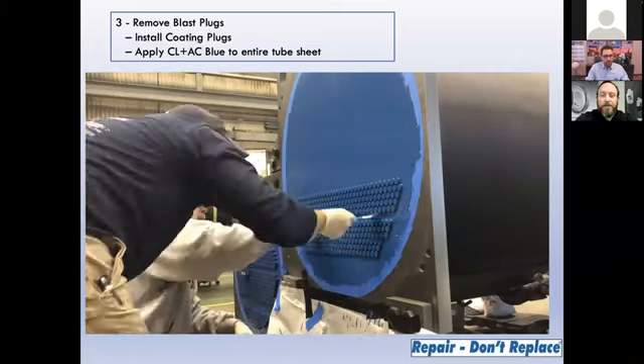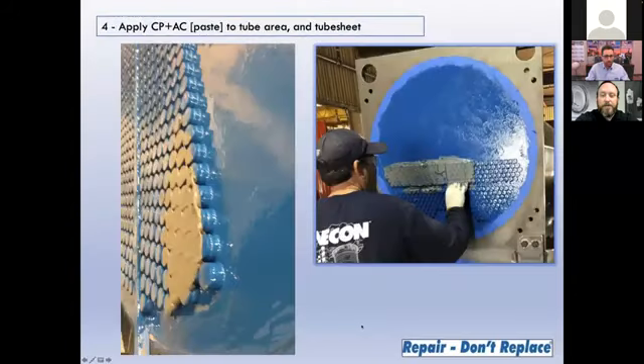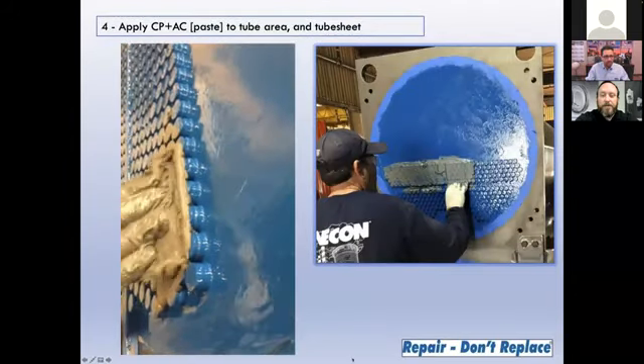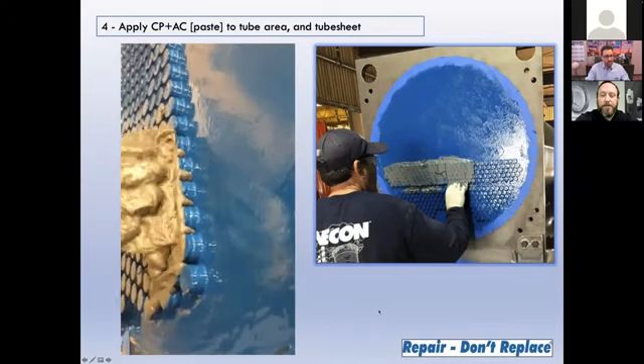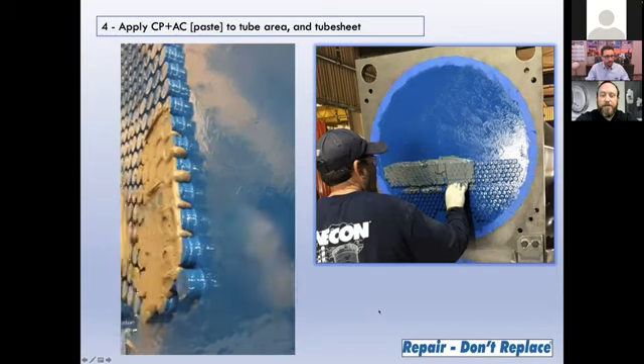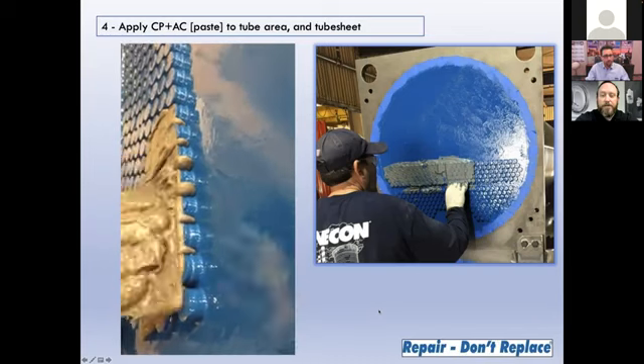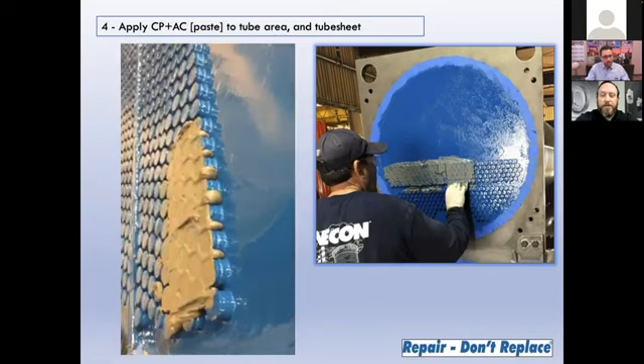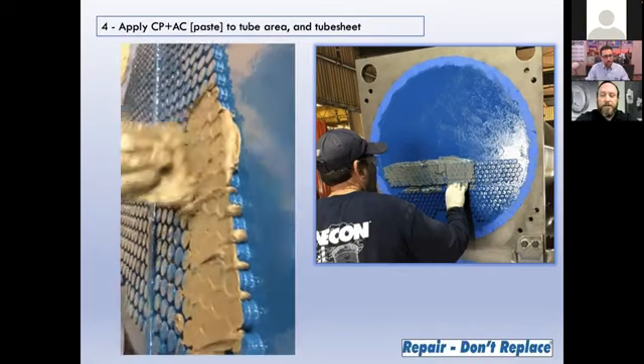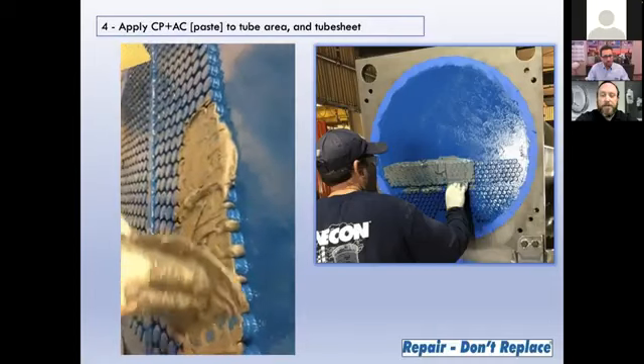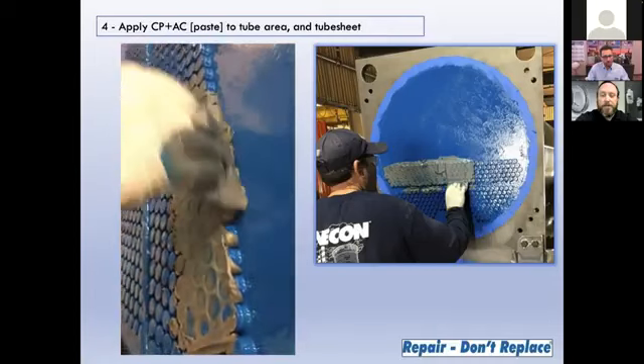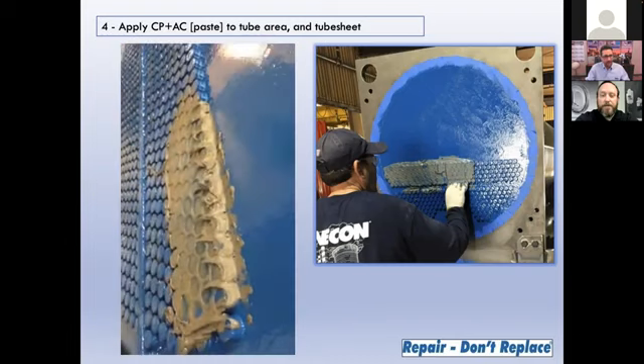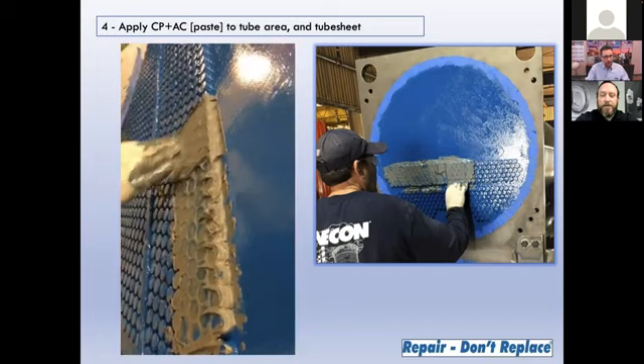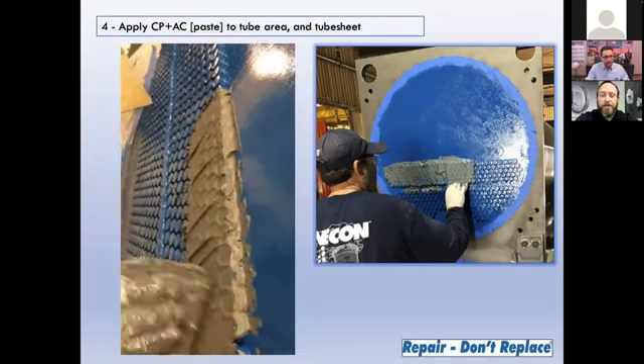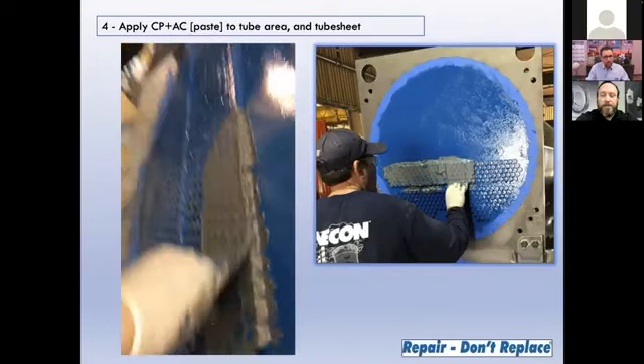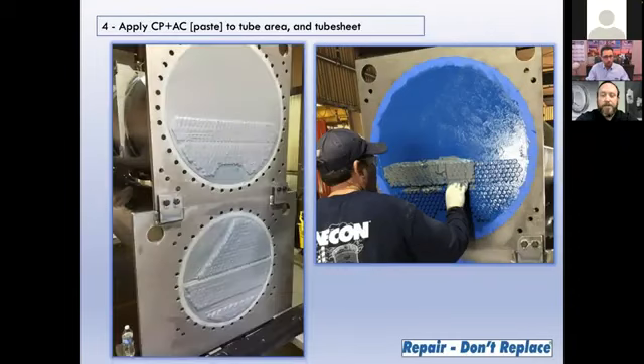The next part of the process is to apply the CP plus AC to the tube sheet surfaces. In this video, you'll see that the CP plus AC is pressed firmly in a vertical fashion, pressing down in between the tubes, getting intimate contact between the tube sheet, the tubes, and the CP plus AC, pressing firmly, going vertically, then horizontally, making sure we get all the possible air out of the system as we're pressing down. What we're trying to do is maximize the amount of product we use and make sure we don't overbuild on top of the plugs too often or too much.